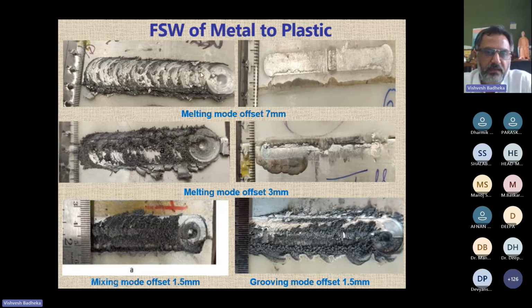You can compare. Here you can see the aluminum and plastic mixing, you can see optimum. Here it has improved further. You can see some islands of aluminum, right? But if you go further, at 1.5, we are very close to the aluminum, very close to the plastic.